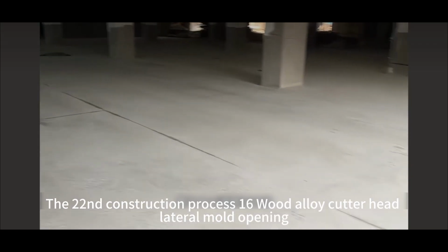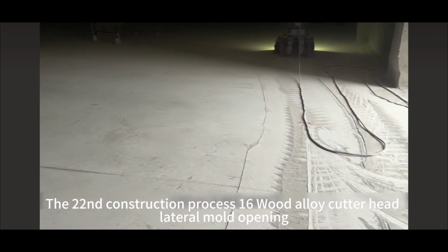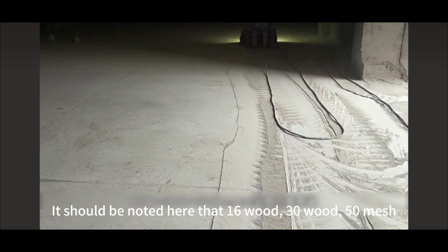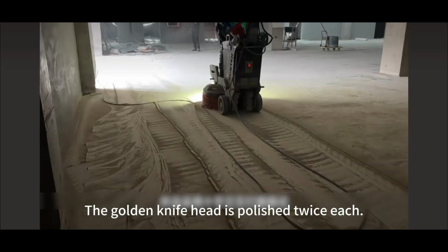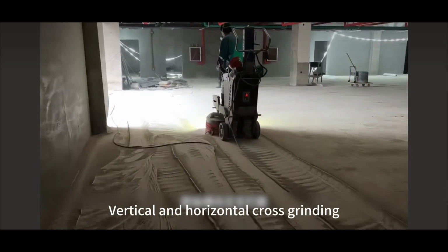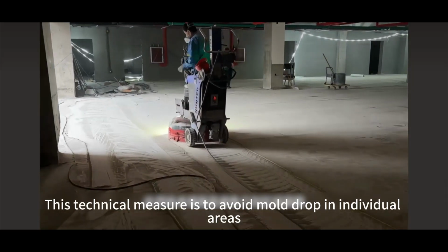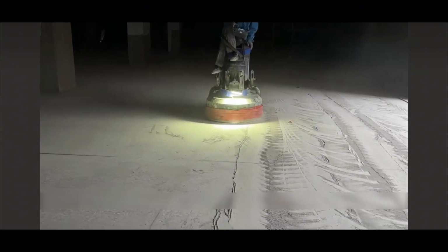The 22nd construction process, the 16 mesh alloy cutter head lateral mold opening. It should be noted here that the 16 mesh, 30 mesh and 50 mesh alloy cutter heads are each polished twice, using a cross grinding path, vertical and horizontal cross grinding. This technical measure is to avoid mold drop in individual areas.